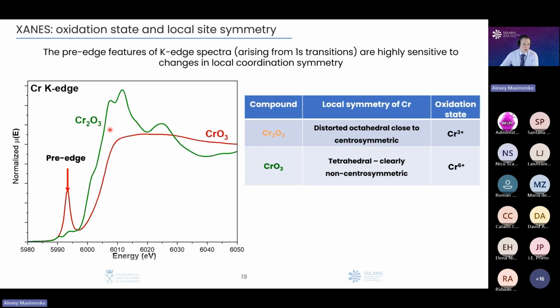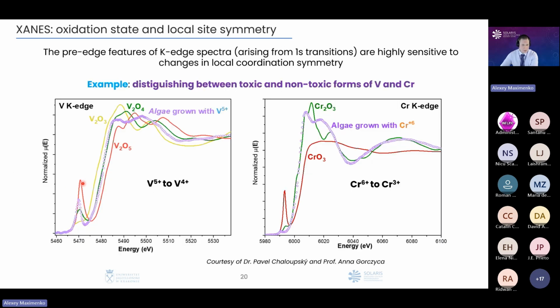The same, for example, we could see for two types of phases of chromium. For example, chromium 3 oxide and chromium 6 oxide, where one of them is, let's say, good for our organism, and the second one is toxic. And having the possibility to distinguish between different phases by analysis of XANES, and especially the pre-edge, allows us to investigate very complicated materials. For example, now it is quite important to clean waters after complicated industrial processes, where we can have in water, for example, vanadium 5, which is toxic, and chromium 6, which is also toxic, and how different plants or algae could transform them from one form to another. And absorption spectroscopy could help us in this case.